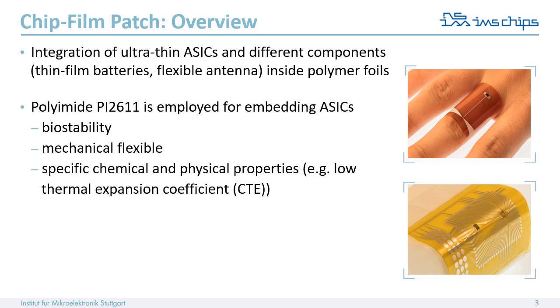To accomplish this goal, the polyimide PI2611 is employed because it provides excellent material properties such as the required biocompatibility, mechanical flexibility, and a low thermal expansion coefficient, which will reduce the process-induced stress during the fabrication. The ChipFilm patch can act as a stand-alone system, as shown in the image before, or as an interposer, shown here on the right side, which can be integrated in another sensor system.